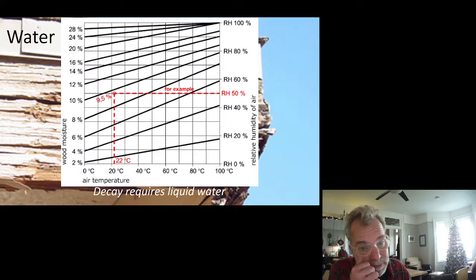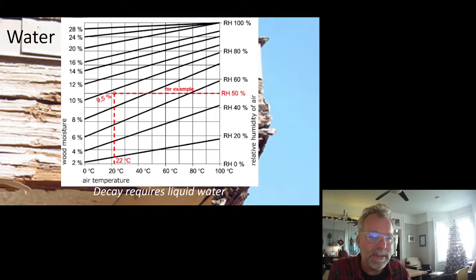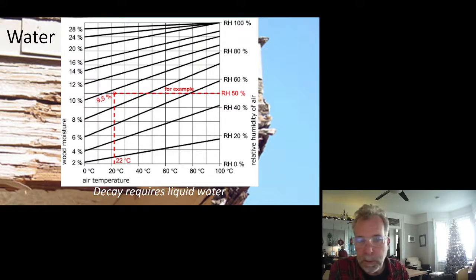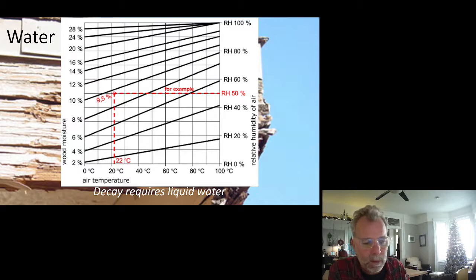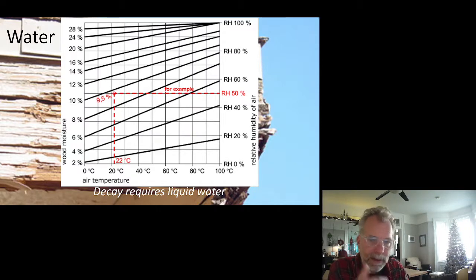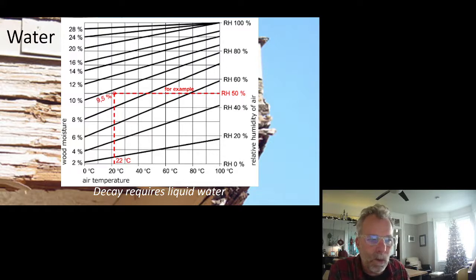To get the wood to 25% moisture content, at room temperature you need a sustained relative humidity of 95% for decay to commence. What does that mean? It means that wood is actually ideal in a pool environment — because in a pool environment you have high humidity but high temperature, and you will not get a humidity high enough for decay to start.